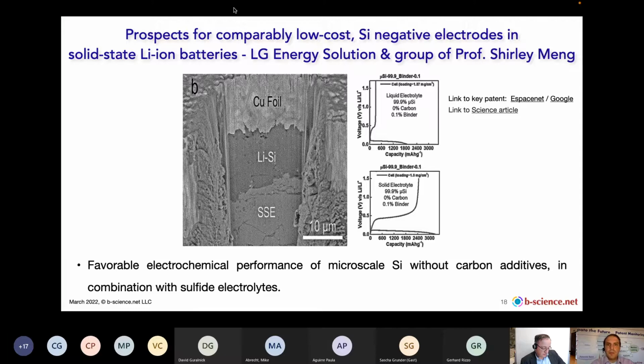Then there is a very interesting result recently by LG Energy Solution and Professor Shirley Meng's group, now at the University of Chicago and Argonne National Labs, where they showed that one can even use silicon microparticles without carbon, and if one uses sulfide electrolytes, they found favorable cycling results, which in a liquid electrolyte system would be pretty much impossible, at least up to now, to achieve stable cycling.